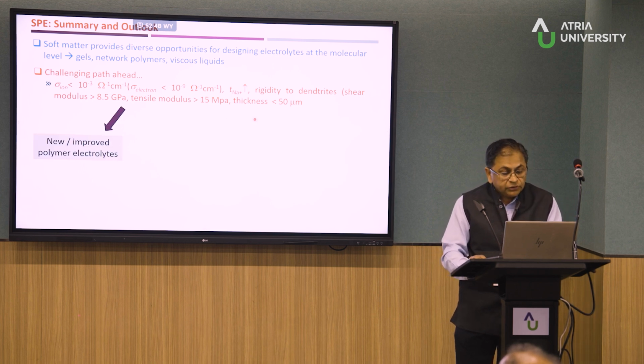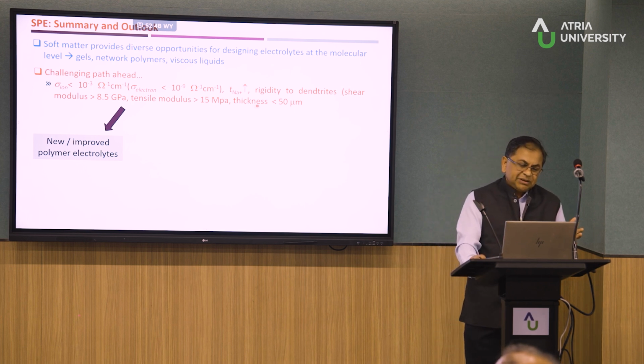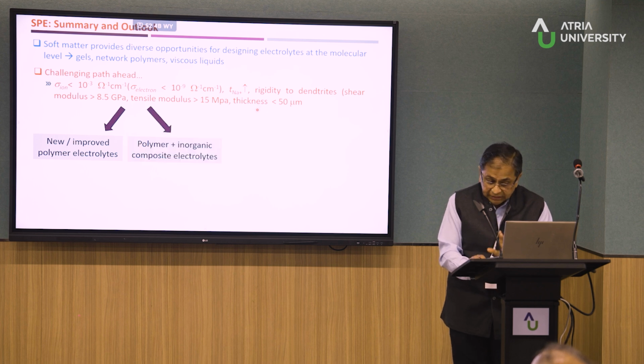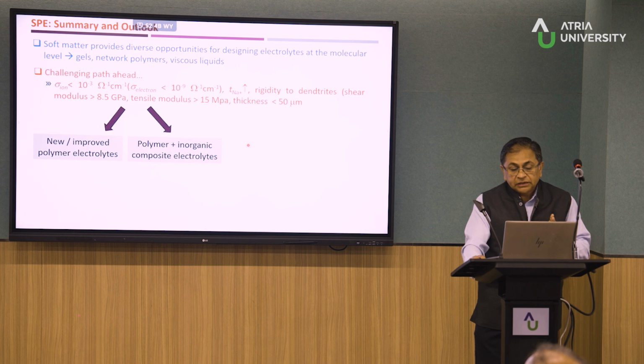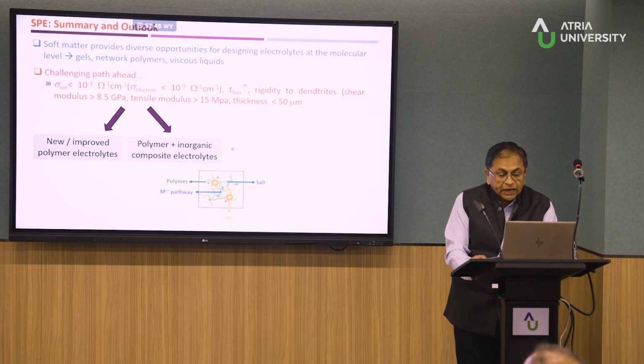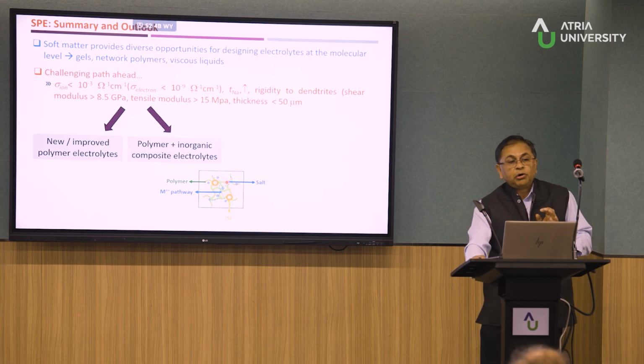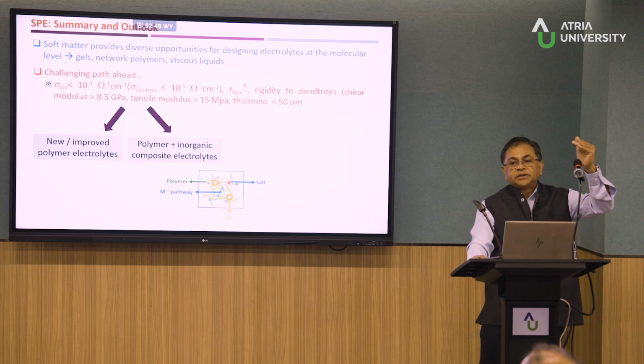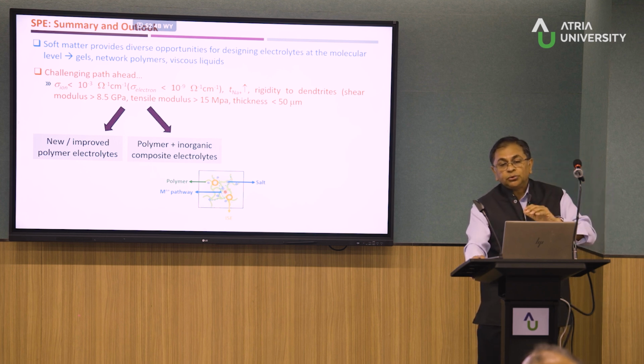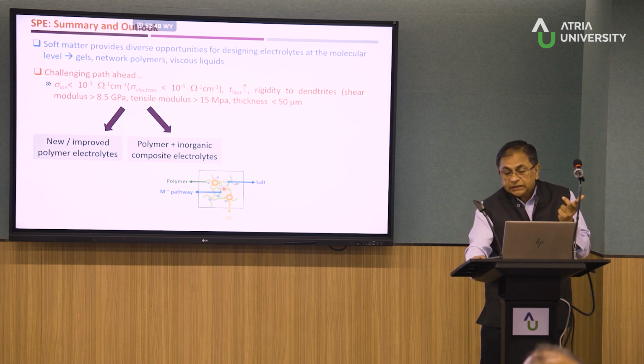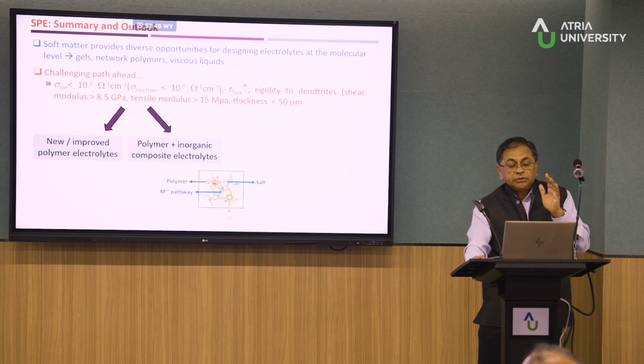So one of the ways, of course, you can still go ahead with newer polymer systems, but that may take half a century. Okay, and I don't think I have the time to wait till that period. So the other way would be, which is something which many in this field are doing, is actually to build systems where you have an inorganic component as a filler. All right. Now, in this domain, I'm not really referring to the old style of work where you have a polymer and you have less than 10% of fillers. So what this is doing is not really altering the effective conductivity of the system. So the conductivity is still quite low compared to, let's say, liquid electrolytes or even solid electrolytes. Why? Because these are not insulating fillers. This is maybe a solid electrolyte itself, a ceramic solid electrolyte.